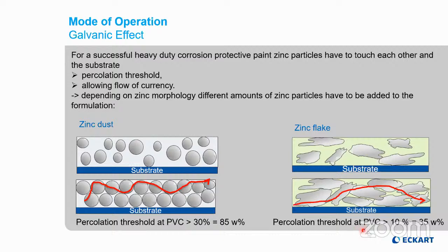We recommend a PVC of 10 to 12% roundabout. Here you see more than 10%, meaning 35% weight loaded into the formulation. And this is absolutely sufficient to generate a percolation threshold in order to guarantee good corrosion protection with zinc flake. So you have, in comparison to zinc dust, and it is really important to understand this change in mindset, lower loading of zinc in your formulation.